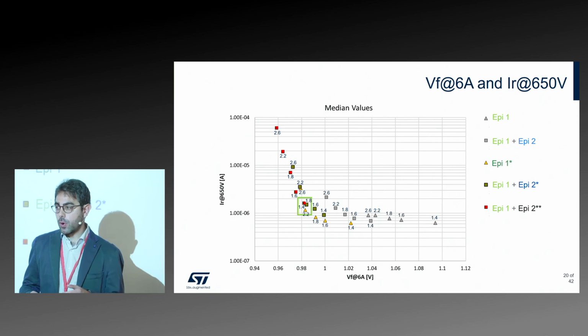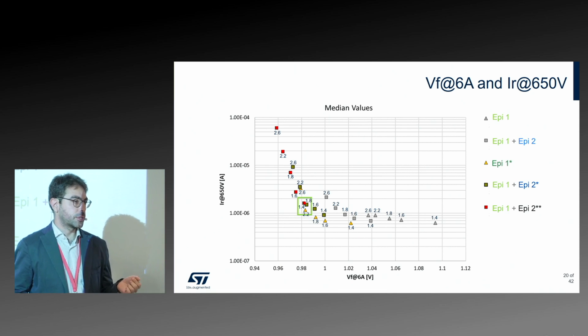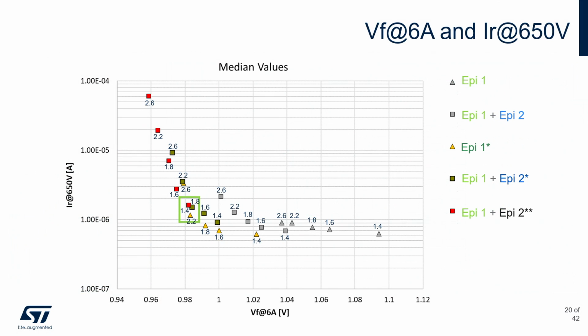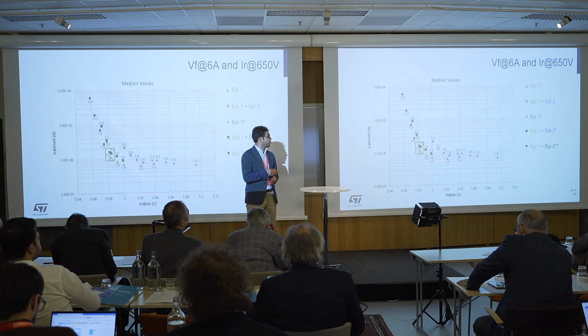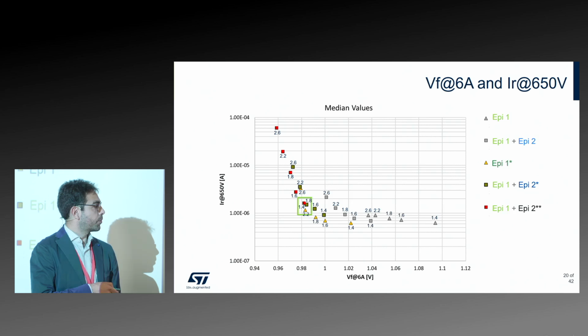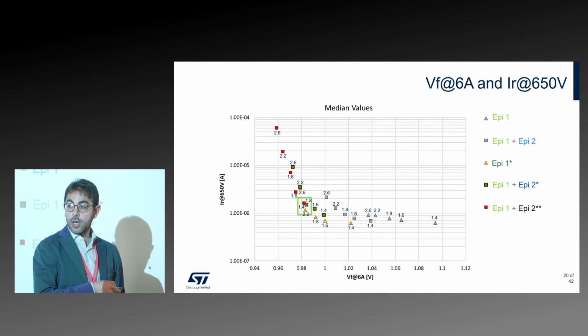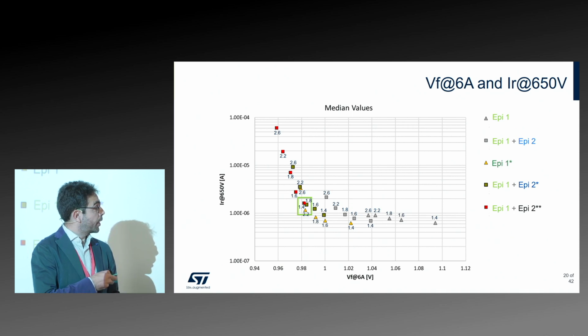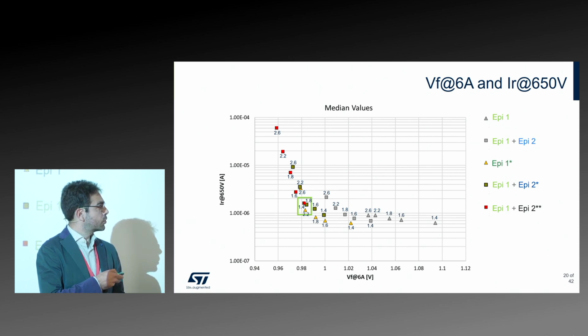But when we design our devices, we are interested not just in the VF, but also in the leakage. So we plot in a correlation plot the leakage and the VF. From this correlation plot, we can get some interesting information. In this area of the plot fall the points in which there is no implant. You can see that the leakage doesn't change much with the pinching, while the VF changes a lot thanks to the pinching. In this area here, we can find the points that have implant, in which the pinching effect plays a key role to control the leakage, but not so much the VF.